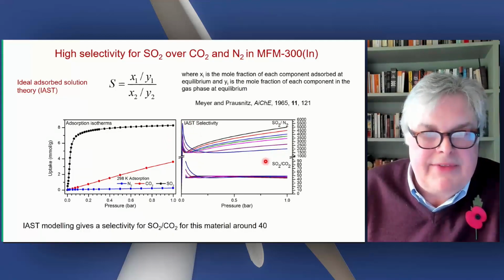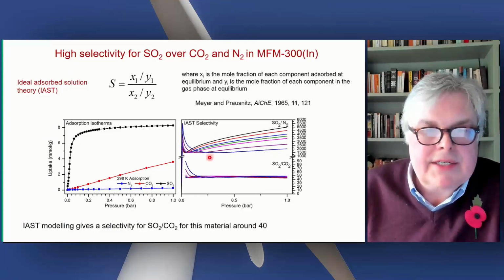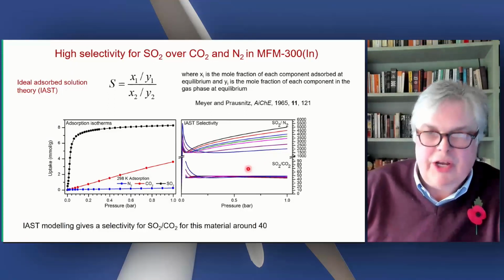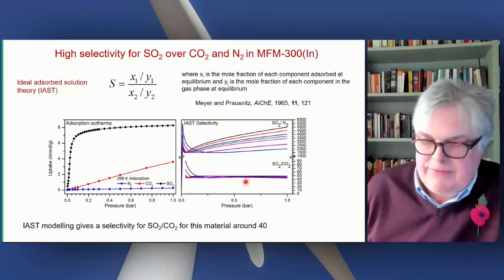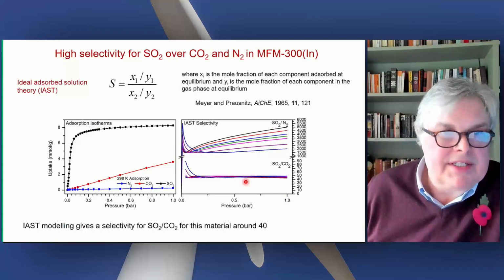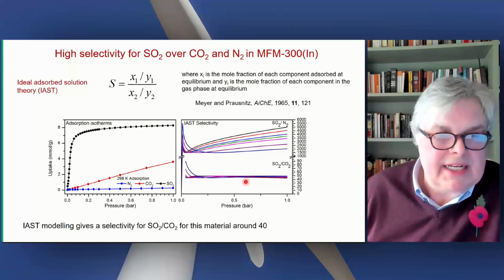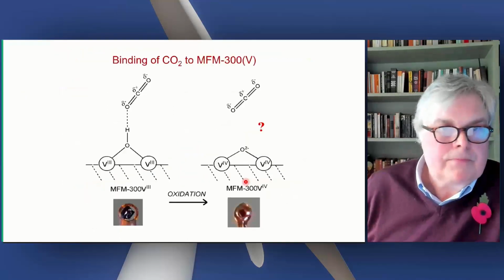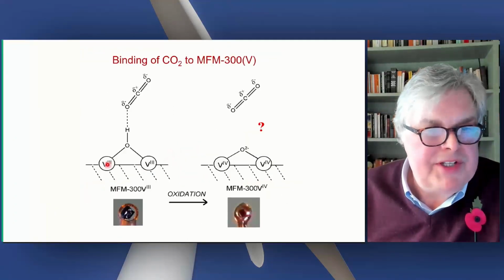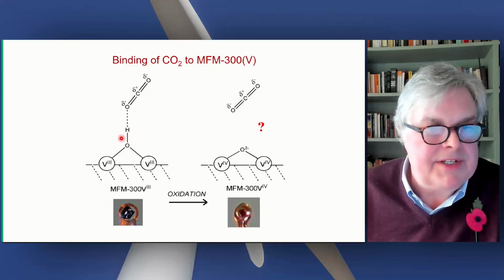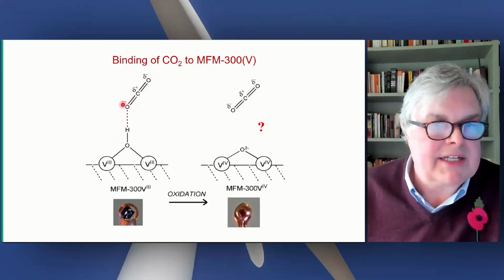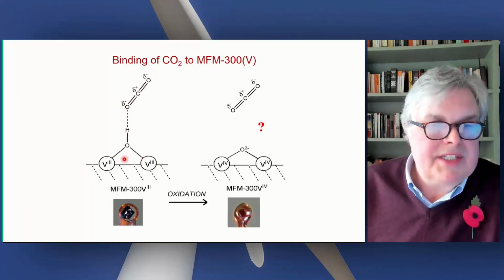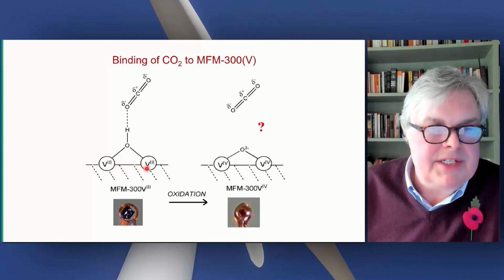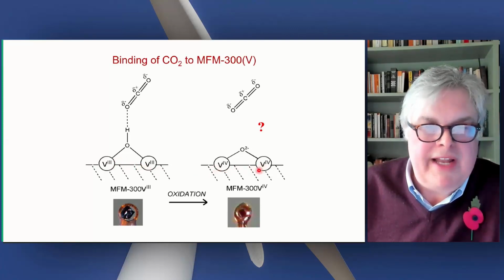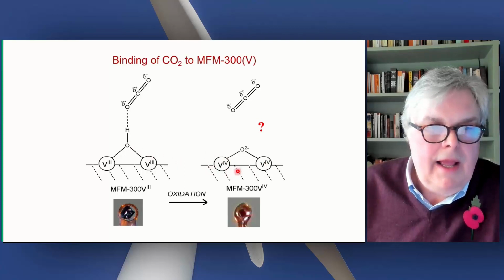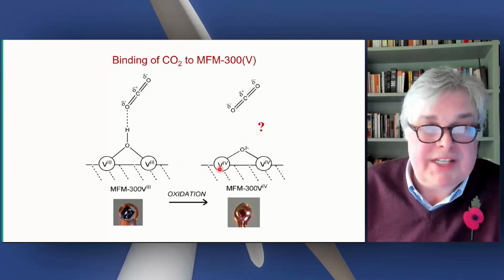So really it's in this middle area that you get a greater accuracy in terms of your analysis of selectivity. But this material has very, very good selectivity for SO2. What happens if you take the vanadium-3 compound? Here is the hydroxy group interacting with the CO2. This material we can oxidize directly to a vanadium-4 species, and to counterbalance the charge, it's isostructural.